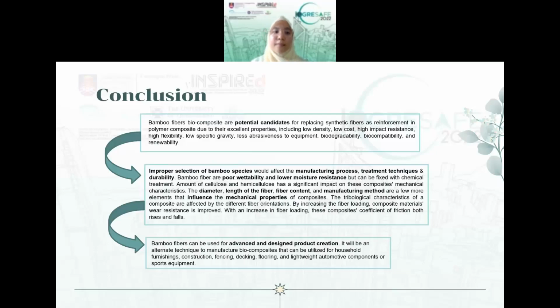But the improper selection of bamboo species would affect the manufacturing process, treatment technique, and durability. This is because bamboo fiber has poor wettability and lower moisture resistance, but it can be fixed with chemical treatments. The amount of cellulose and hemicellulose also has a significant impact on the mechanical characteristics, and the diameter, length of fiber, fiber content, and manufacturing method are also elements that influence the mechanical property of composites.